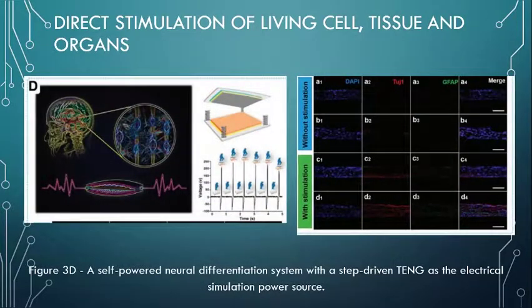Zhang and others reported a biodegradable triboelectric nanogenerator for short-term stimulation of neural cells in vivo. The output voltage and current of BD-TENG were approximately 40 volts and 1 microampere respectively. When two complementary micro-grating electrodes were powered by BD-TENG, a 1 Hz and 10 volts per millimeter DC pulse electric field, or EF, was generated. This DC pulsed EF oriented the growth direction of nerve cells cultured on the micro-grating electrode successfully, which was crucial for neural repair.